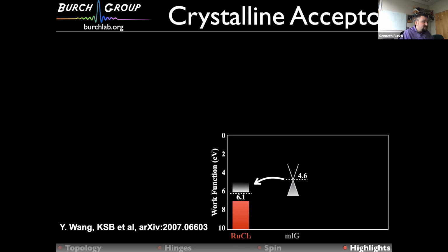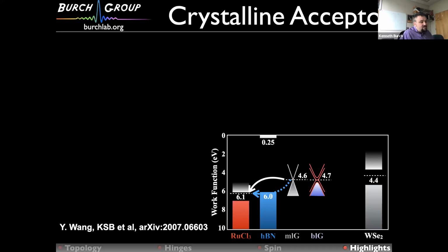And so I expect a large charge transfer from the monolayer graphene into ruthenium chloride, and similarly from bilayer graphene. It turns out that hBN, its valence band lines up roughly with ruthenium chloride, and so therefore you can also get a lot of charge transfer from the monolayer graphene into ruthenium chloride, even if the hBN is in the way, at least cartoonishly. There's nothing special about monolayer graphene. Tungsten selenide should also do this.